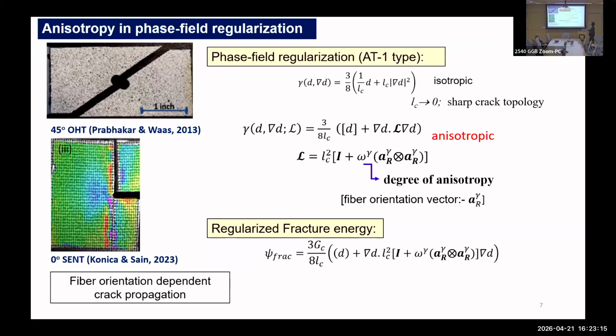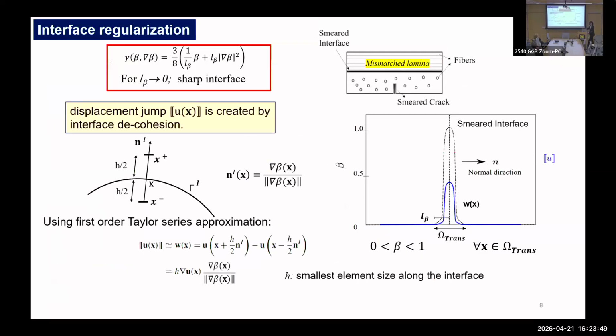Here, a gamma is the fiber orientation vector. All it says is that if the gradient tries to align parallel to the fiber direction, then we have a higher energetic penalty. So it will try to align the gradient orthogonal to the fiber direction, and so it will align the crack growth along the fiber direction. Now the regularized fracture energy has an anisotropic form, and if omega gamma is 0, then you get back to the isotropic form. So this was for the anisotropic crack growth.